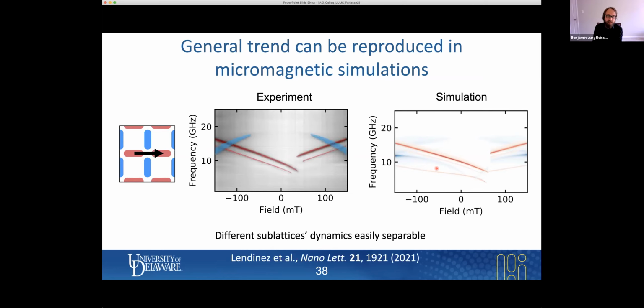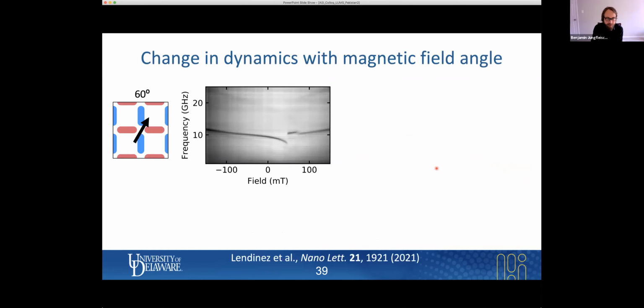I'm superimposing this here on the experiment. Now, this is not particularly useful for 0 degrees because we can use the analytical formalism, but it becomes much more challenging to analyze if there is an in-plane field angle. I'm showing this here for 60 degrees, and you see the modes become flatter. And there is a step-up feature here when the elements switch, and then there's a step-down feature in the resonance spectra. So where is this coming from?